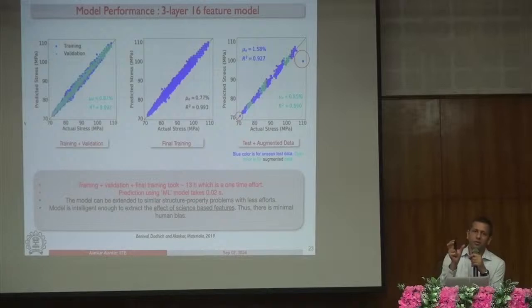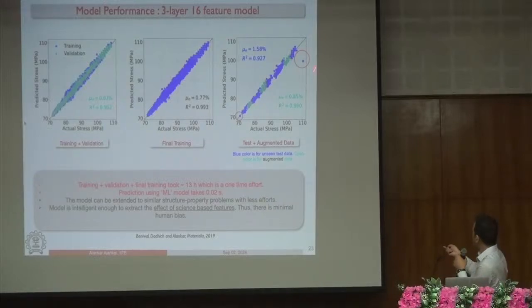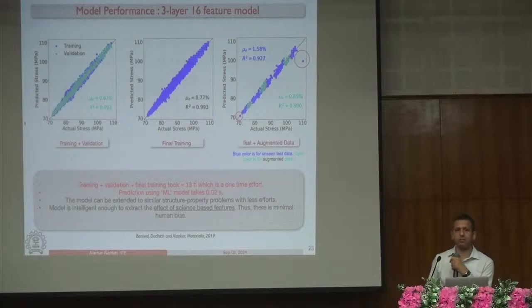The reason was that when you look at 0%, there is no geometric nonlinearity. Those black phases that have been introduced in the microstructure have not participated there at all. However, if you look at this part where there is 100% black phase, the model was not able to extrapolate to that. It failed. The prediction is here. Actually, it should have been here, so it is under predicting it. Right? Fairly decent job still.